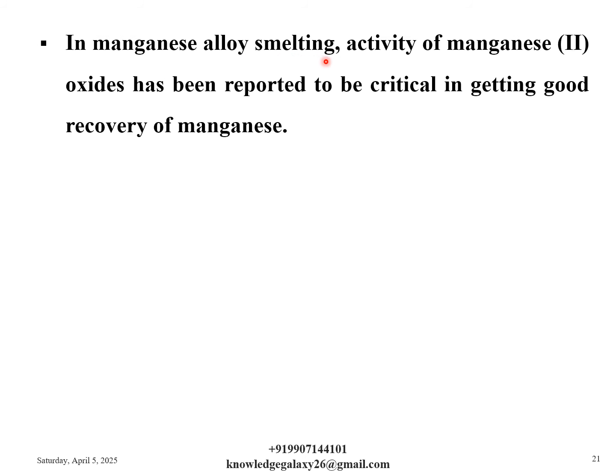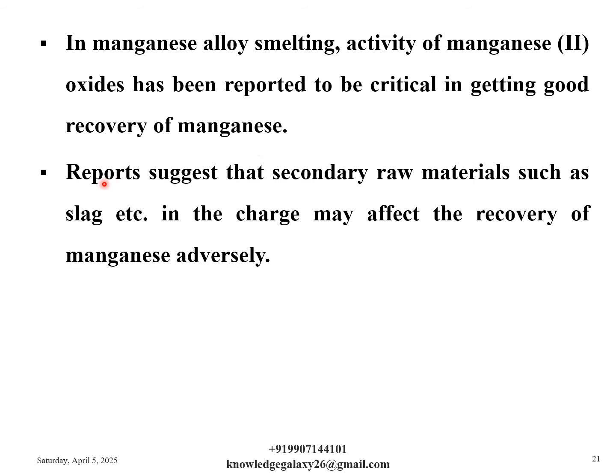In manganese alloy smelting, the activity of manganese oxide has been reported to be critical in getting good recovery of manganese. Reports suggest that secondary raw materials such as slag in the charge may affect the recovery of manganese adversely. Here the slag refers to high carbon ferromanganese slag.